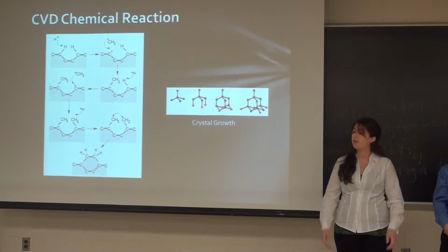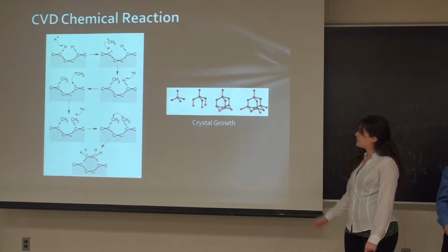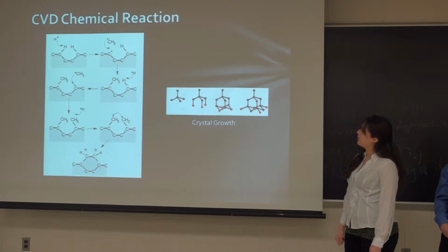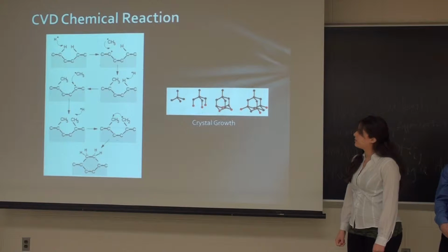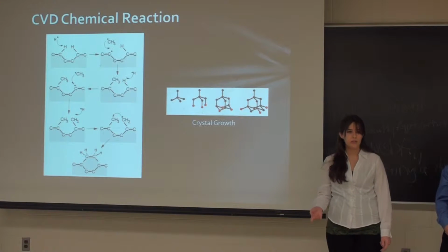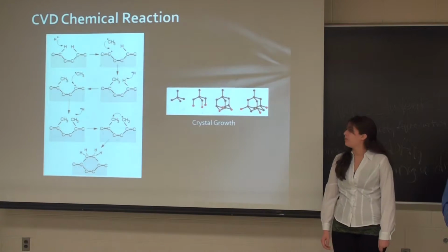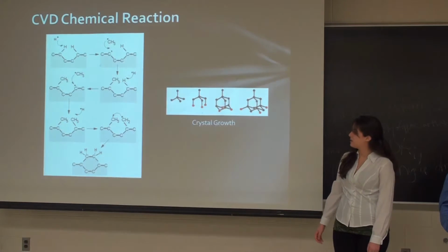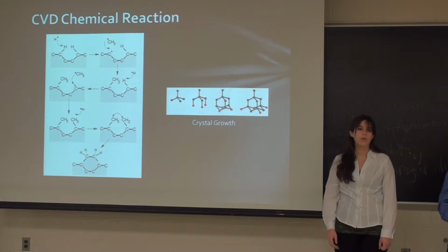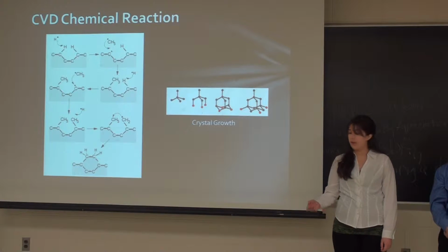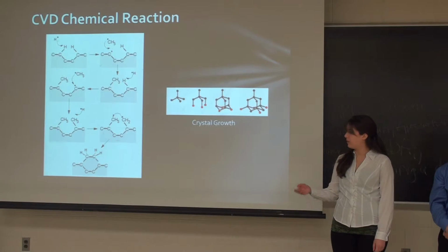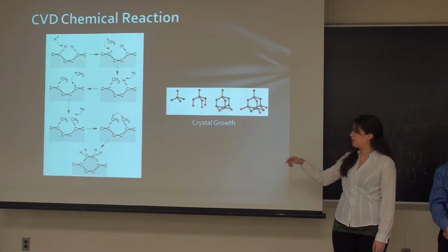Nothing happens, essentially. However, the first three images in this diagram show how when hydrogen is removed from the existing diamond structure, CH3 is able to bond. If CH3 bonds in two adjacent spaces, and then more hydrogen in the atmosphere combines with one of the hydrogen atoms in the CH3 to form CH2, the CH3 and CH2 are able to combine so that there is a strong bond between the carbon atoms.